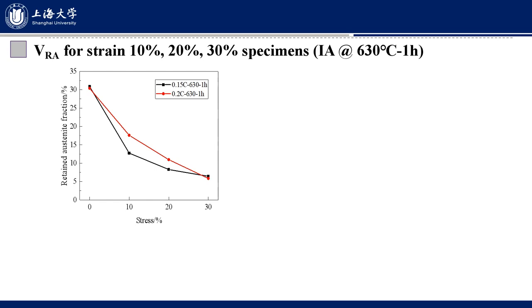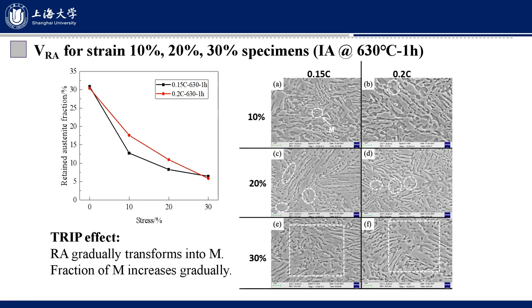This slide shows the volume fraction of retained austenite for strains of 10%, 20%, and 30% specimens. It is clear that the retained austenite fraction decreases with the strain increasing. It is clear that the TRIP effect occurs. The retained austenite gradually transforms into martensite, and the fraction of martensite increases gradually, both for the 0.15 carbon content and 0.2 carbon content steels.